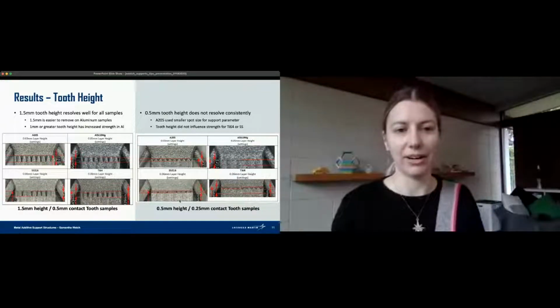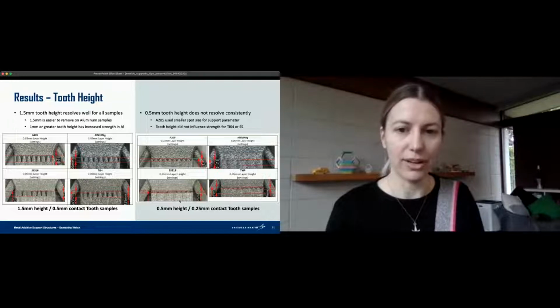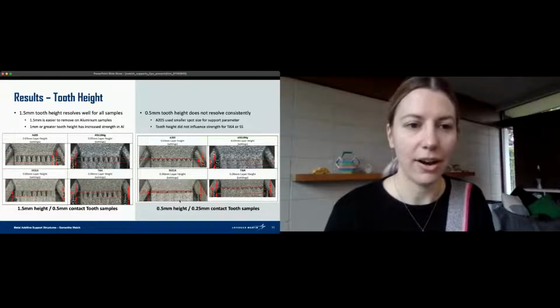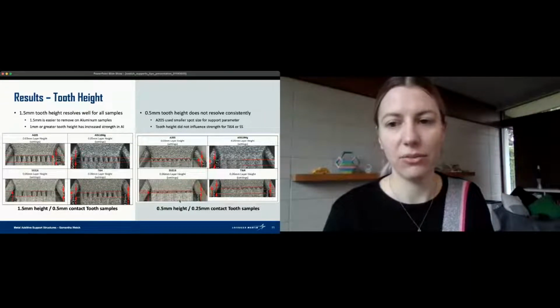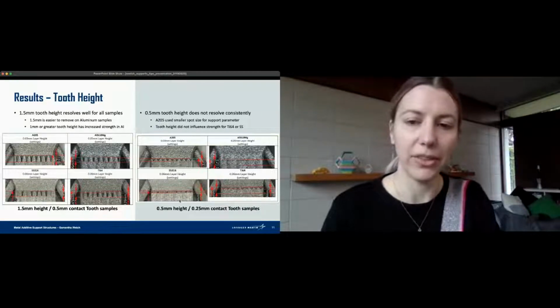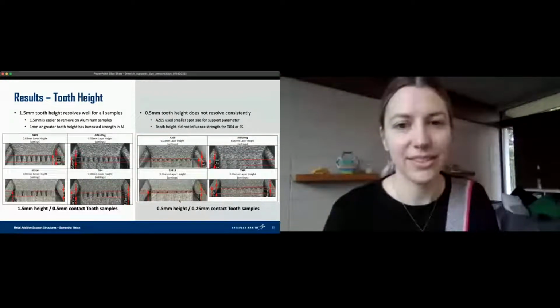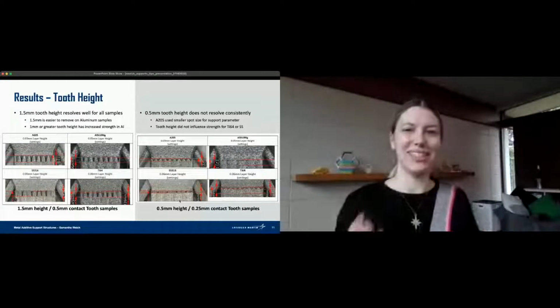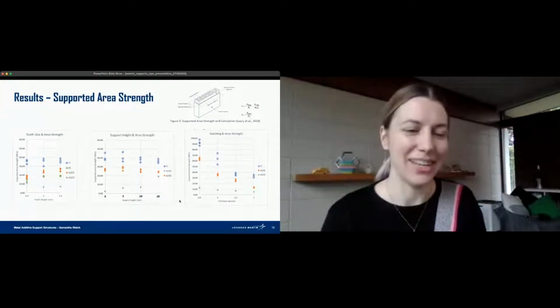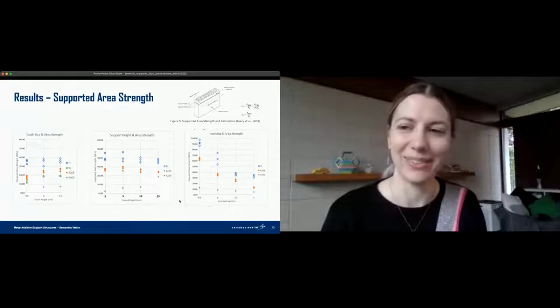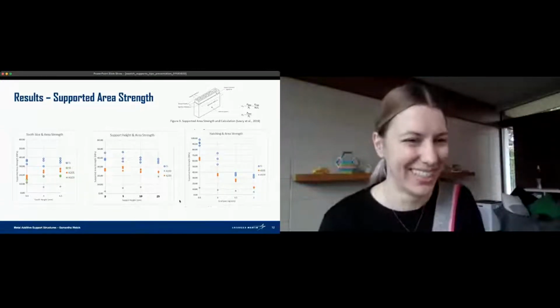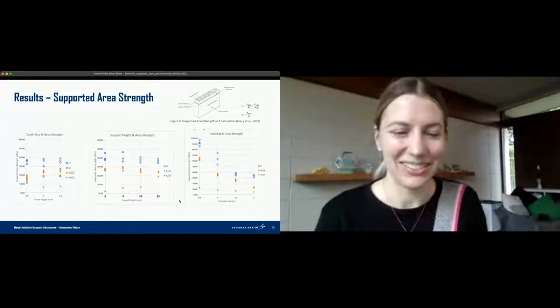So overall, I recommend if you're looking at this support interface region, these larger size interfaces tend to be more robust and repeatable than these smaller ones. And this is some of the data. It's funny when you get all these samples, it seems like it's just an endless amount of samples to process. And then you actually look at the data and you're like, well, I wish I had way more samples. So that's the curse of any study.